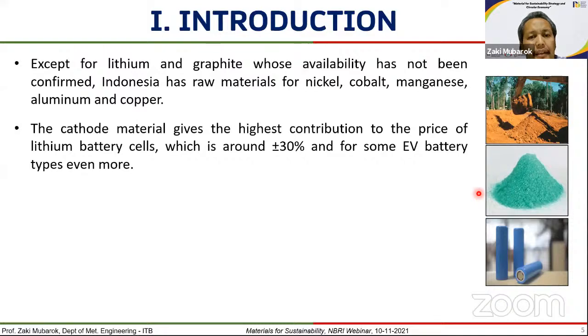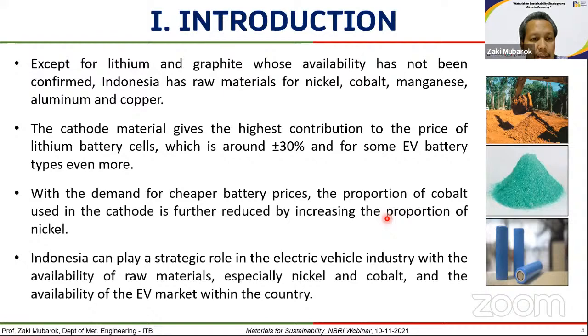The cathode material gives the highest contributions, as I have mentioned before, and with the demand for cheaper battery price, the proportion of cobalt used in cathode is further reduced by increasing the proportion of nickel. So the trend is to utilize cathode material with higher proportion of nickel, such as nickel, manganese, cobalt with 8:1:1. The mole proportion: nickel 8, cobalt 1, manganese 1.